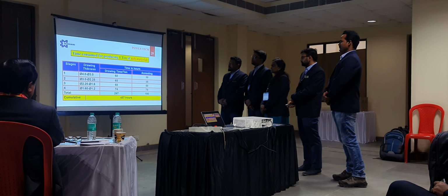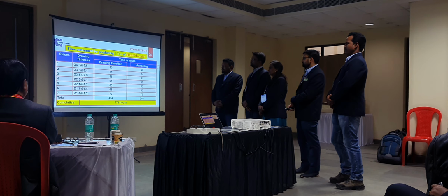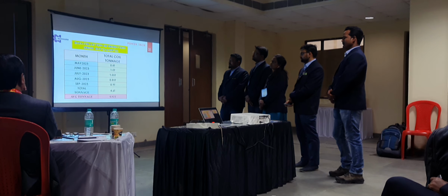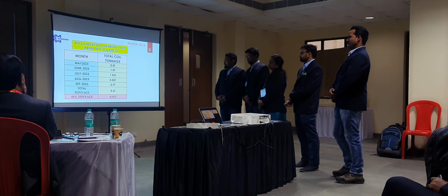Time consumed for producing 1 ton of soft material in 4 stages, drawing the thickness from 4 mm to 1.2 mm, is 457 hours. Similarly, time consumed for producing 1 ton of hard material, drawing the thickness from 4 mm to 1.2 mm in 7 stages, is 774 hours. This is the data collection of production from May 2023 to September 2023.